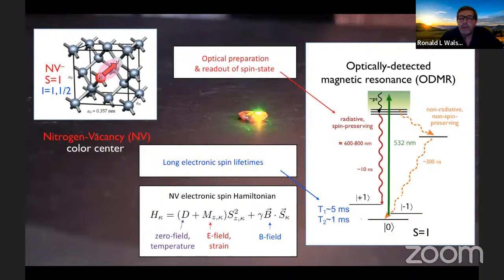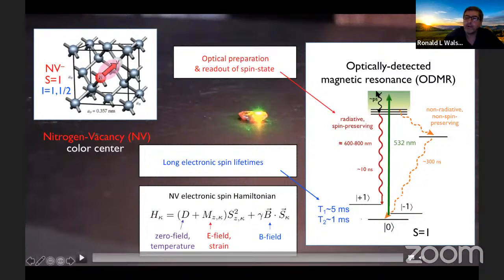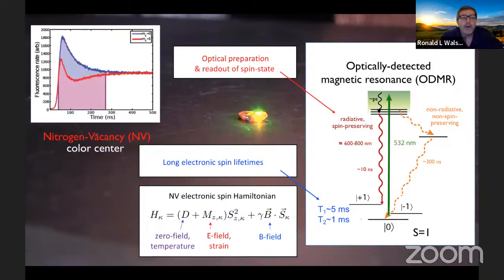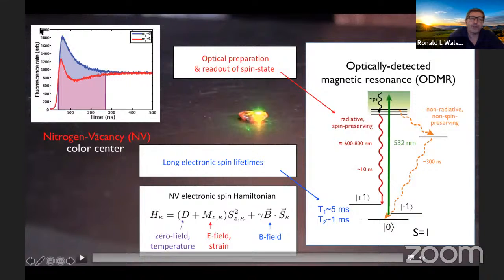Also key is the ability to optically prepare the spin states and read them out, which is related to the branching ratios and the differential branching ratios in the excited state in a way I'm going to describe now. So on the left, I'm showing you some data that's taken from a single NV and repeated over many runs of the experiment. And this shows the fluorescence rate, the emission rate of red photons on the y-axis, and time in nanoseconds along the x-axis. And there's 2 data traces shown.